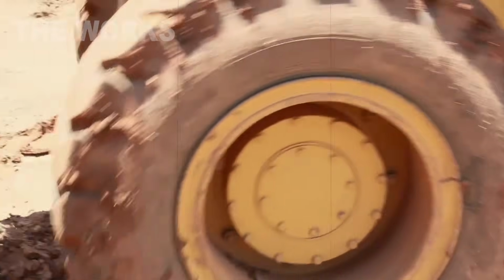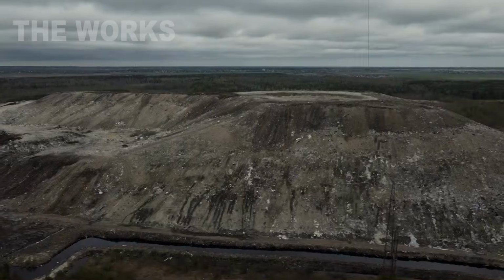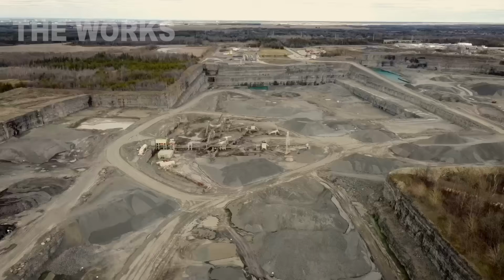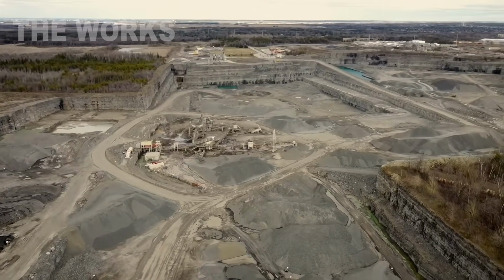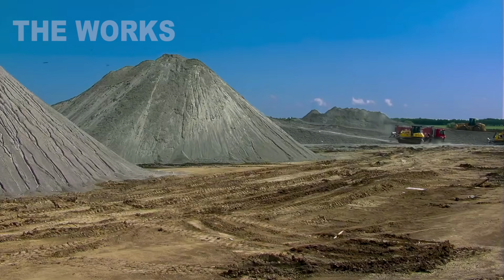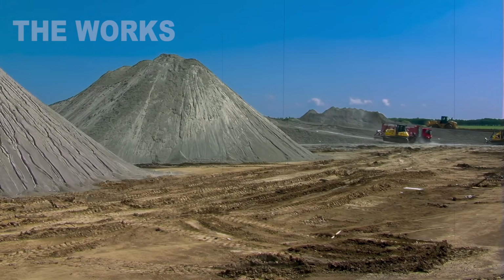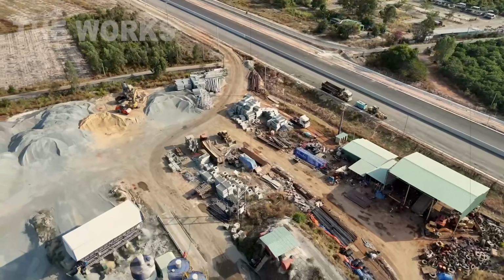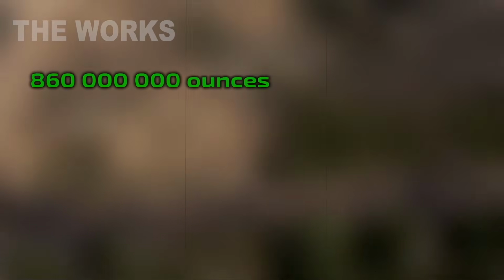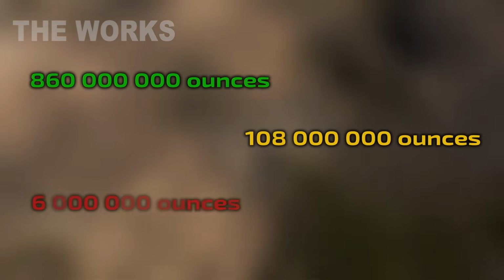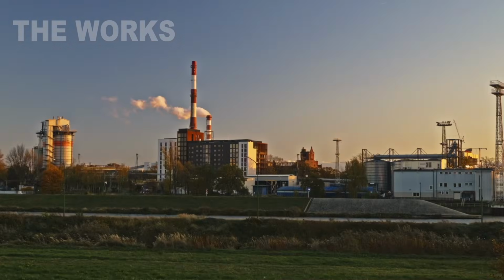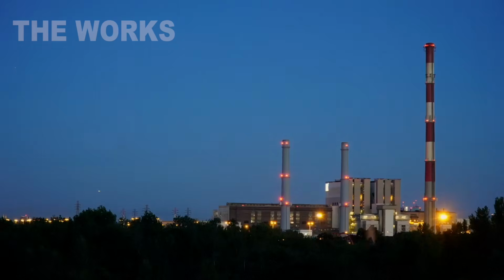When comparing the rarest precious metals by annual mine production, platinum is far rarer than gold. We're talking about more than 15 times rarer by annual output. In 2018, silver, gold, and platinum mine production totaled 860 million ounces, 108 million ounces, and 6 million ounces respectively. Producing a single ounce of platinum requires about 10 tons of ore. For comparison, gold needs around 2 to 3 tons of ore to produce 1 ounce, while silver takes 5 to 10 tons per ounce.